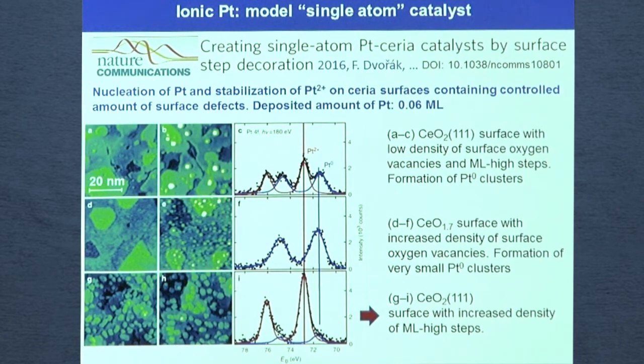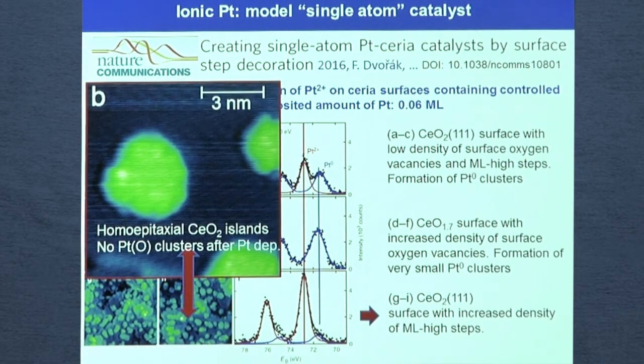Well, and the third example here shows stoichiometric cerium oxide with very high density of steps, and you can see that by depositing the same amount of platinum, it is completely oxidized, so we have only platinum 2+. And if we check these islands, we can see that we have monolayer high islands of ceria, but we don't see any platinum particles because the platinum is atomically dispersed around.